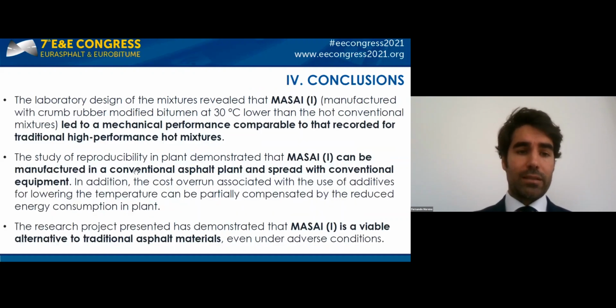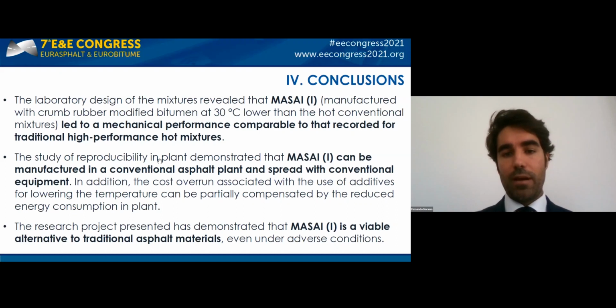As a conclusion, we can say that the laboratory design of the mixture revealed that MASAI grade 1 led to a mechanical performance comparable to that recorded for traditional high-performance hot mixtures, in spite of being manufactured with crumb rubber modified bitumen at 30 degrees lower than the hot conventional mixture. The study of reproducibility in plant demonstrated that MASAI grade 1 can be manufactured in a conventional asphalt plant and spread with conventional equipment. In addition, the cost overrun associated with the use of additives for lowering the temperature can be partially compensated by the reduced energy consumption in plant.